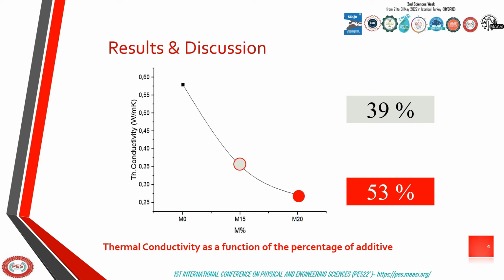The thermal conductivity of the bricks is presented in the figure. The results show that the bricks with biomass additive reach a conductivity of 0.27. The thermal conductivity is reduced by 53% using 20% of biomass additive. The decrease of the thermal conductivity is associated to the formation of pores. In fact, the thermal conductivity decreases because of the low thermal conductivity of air in the newly formed pores.